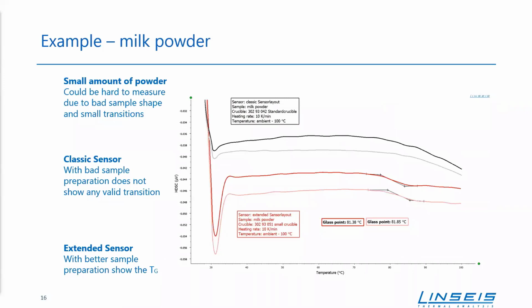So maybe another sample, it was quite a hard sample, the milk powder. So we use standard milk powder. Normally it's pretty easy to measure, but we just have really small amounts of sample here. And also it's a powder at all. So the contact of the sample with the crucible and the sensor at all isn't that good.